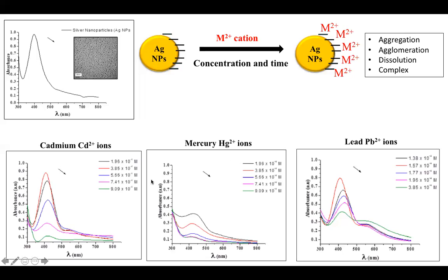And these were all done at about 10 to 15 hours to compare what they look like. And then when we look at lead, again, there's a shift and broadening of the peak, but we also see that secondary peak starting to form. So that can be an indication of a different form, agglomeration, or complexity of our nanoparticles that are there. All these things give insight that our silver nanoparticles are not as stable as what we look at naturally, which is expected because of the charge on that surface.